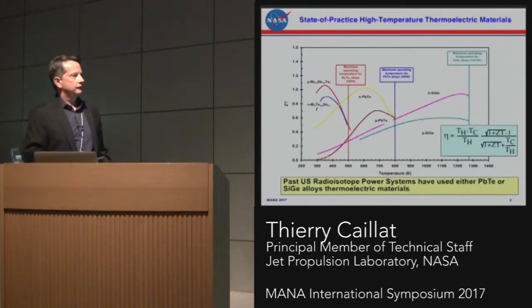State of the art, there's not a single material or set of materials that actually operate all the way to 1,000 degrees C. So sometimes we like to grade or segment some of those materials to take advantage of a full delta T. The Voyager spacecraft, for example, is using silicon germanium, and the MMRTG is using lead telluride based thermoelectric materials. All of these have a limit, both in terms of thermal stability, but also in terms of achieving long life for those devices.